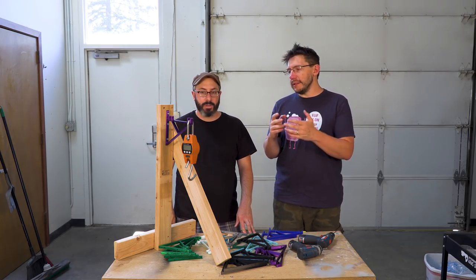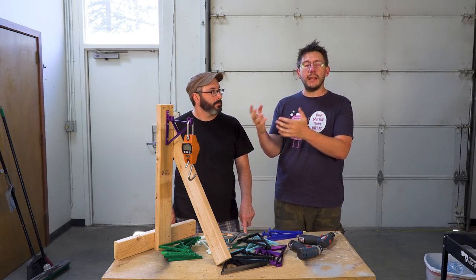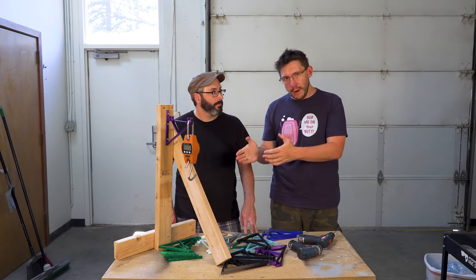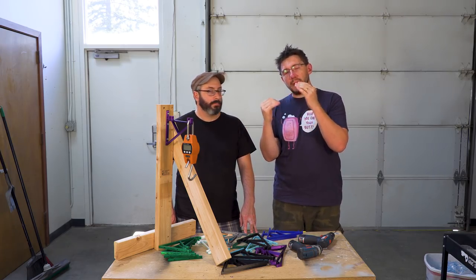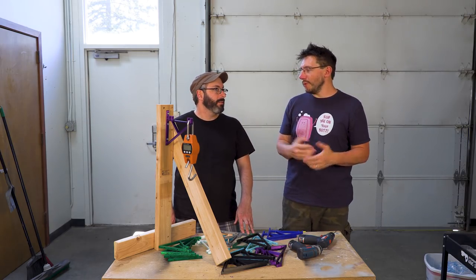Yep. And the scale, when you're pulling down, it's going to give you a measurement, but it's not going to maintain the highest measurement when something breaks or when you let go. So what we can do is record at a high frame rate, and once it gives way, we hit stop on the camera, and then we go through the footage to find out the number that the scale read before catastrophic failure. Right before it broke. Or before we give up.